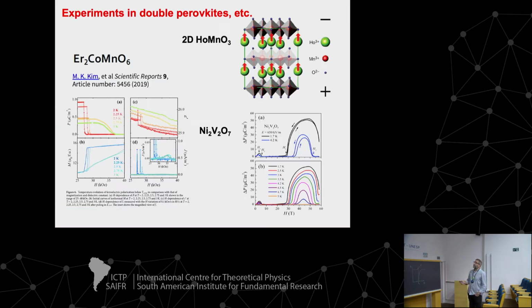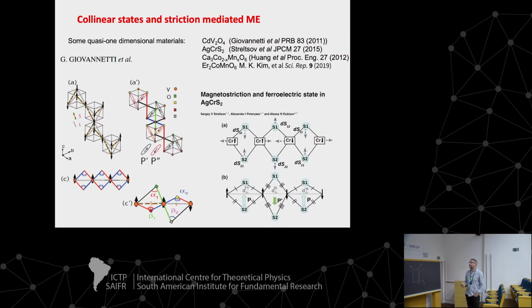OK, so for the experiments, for example, this is one of the double perovskites, which is quasi-1D. And in this paper, they have shown what I have just drawn there. So you see, you vary the magnetic field. Magnetization increases abruptly at the same time that electric polarization drops off, okay? So we are going to try to discuss a simple model that has these two features: the double transition together with this magnetic ordering.